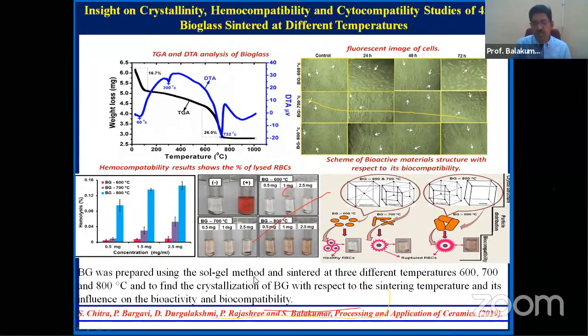Just for the sake of understanding, when you develop a material with a wet chemical method, right after the preparation and before going for annealing, we normally do the TG analysis to see the weight loss. The weight loss in turn gives you the onset of the phase formation. Once you get that number, you can anneal at different temperatures, which gives many different morphologies. In this case, TG shows around 750, and after that we annealed at 600, 700, and 800. You can see the morphologies are different, the sizes are different, the surface area is different, and the structures are different.